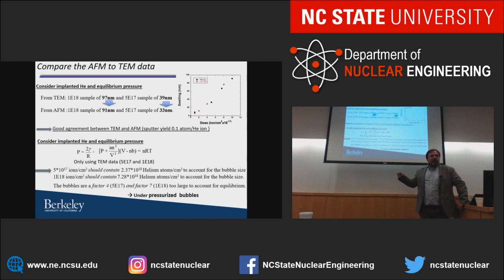Which means the bubbles are not in equilibrium pressure, they're below equilibrium pressure. And the same is true for higher doses, even so the factor between the two is actually much higher, it's even a factor of 7. So our bubbles are under-pressurized. Well, why would that be? Now, one thing, when we implant ions into a surface, we don't just put the ions in there, we also create a lot of vacancies and interstitials at the same time.